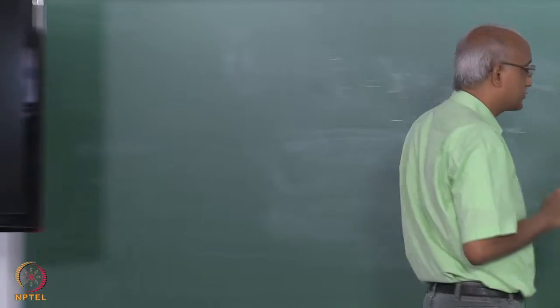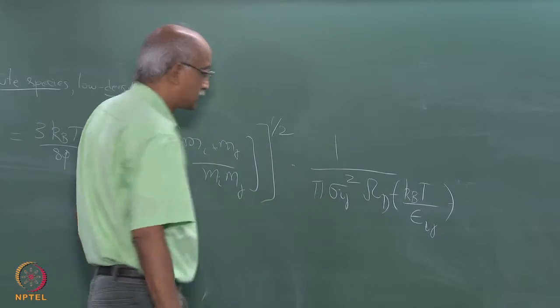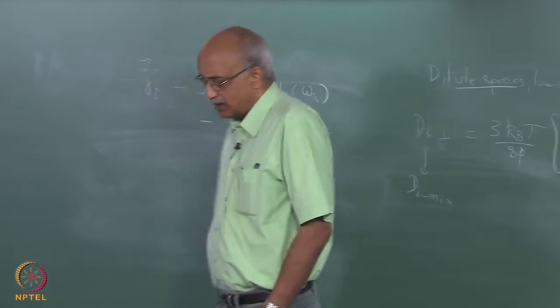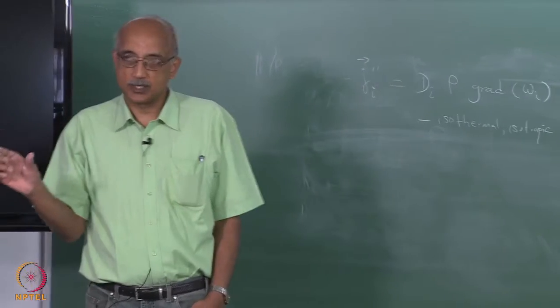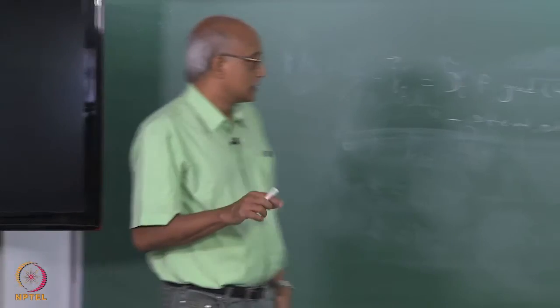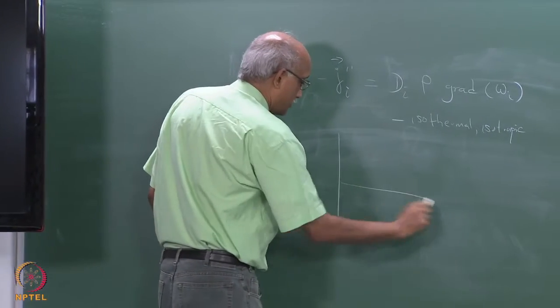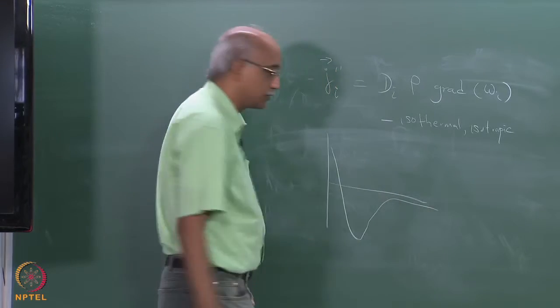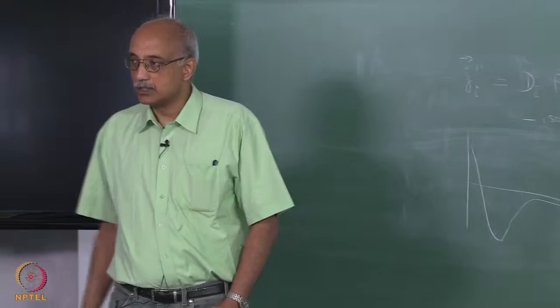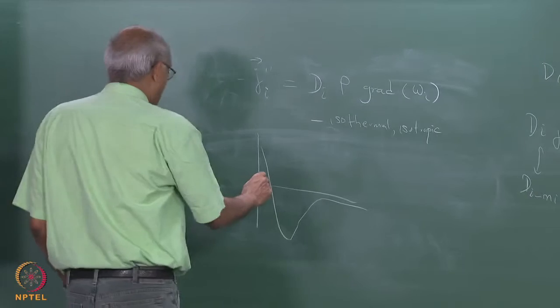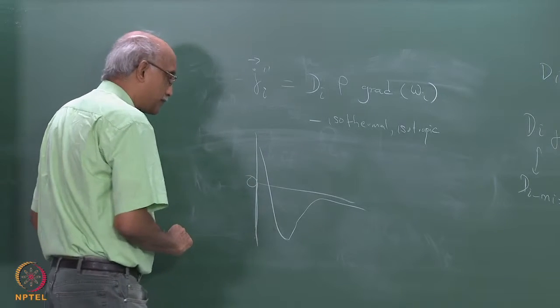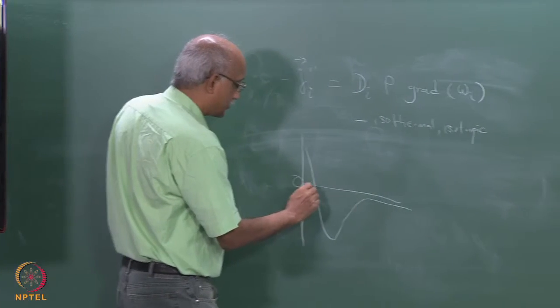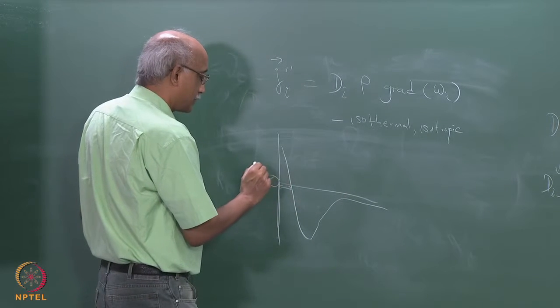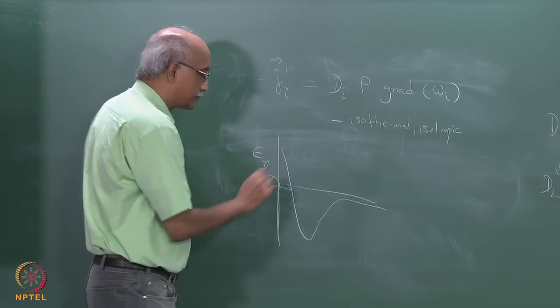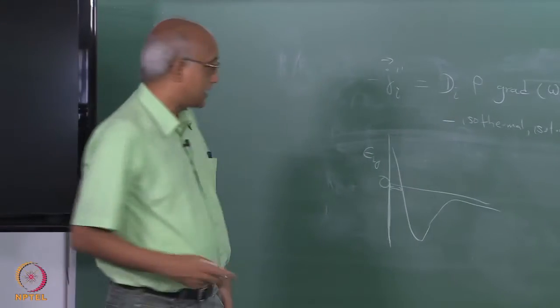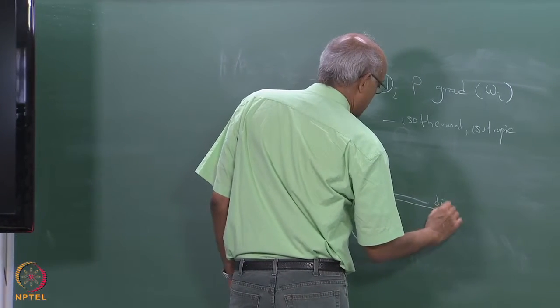The other thing you need to keep in mind is because we are talking about a binary diffusion process, there is this term called sigma_ij. What that reflects is the equilibrium distance of separation between two molecules. So, if you look at the force between any two adjacent molecules, van der Waals force for example, it will follow this typical pattern where 0 is here and there is a particular distance of separation between the two molecules. So, what we are plotting here is essentially the epsilon_ij or the intermolecular potential as a function of the distance of separation.